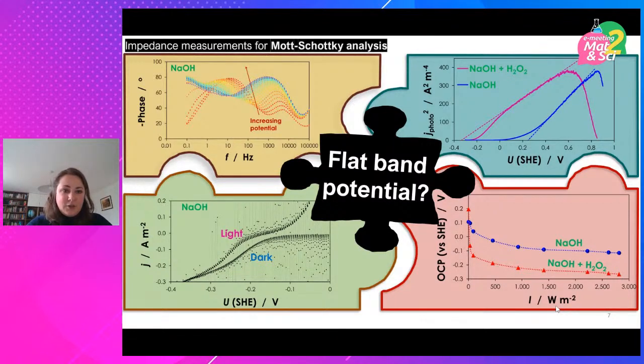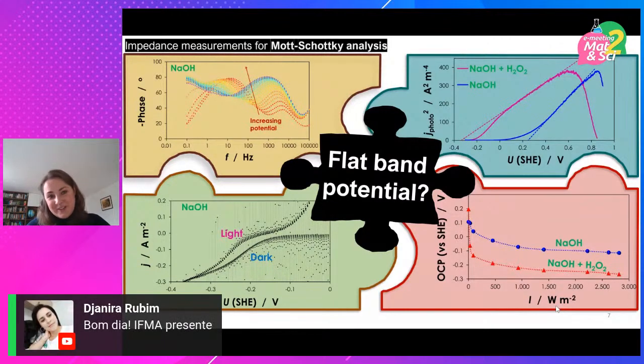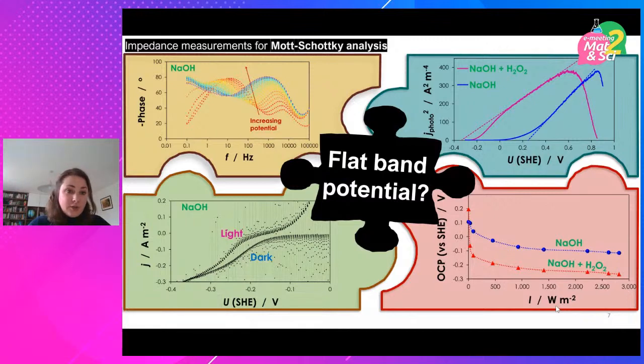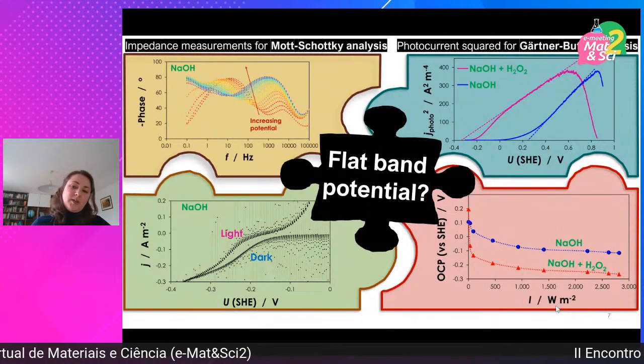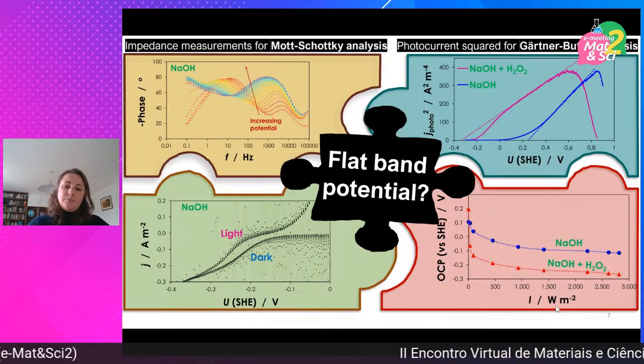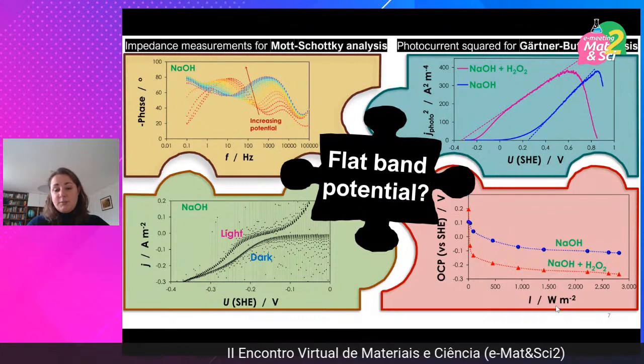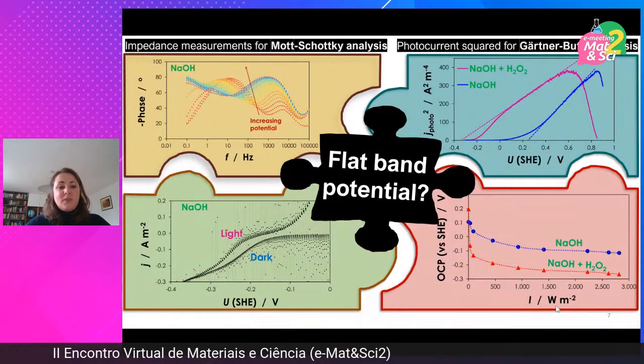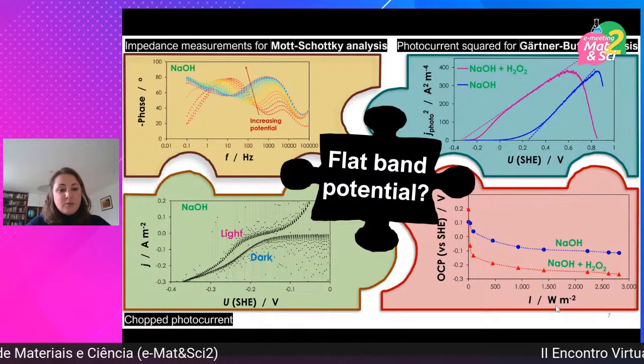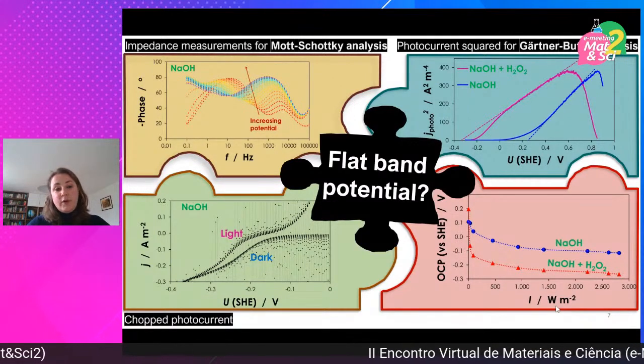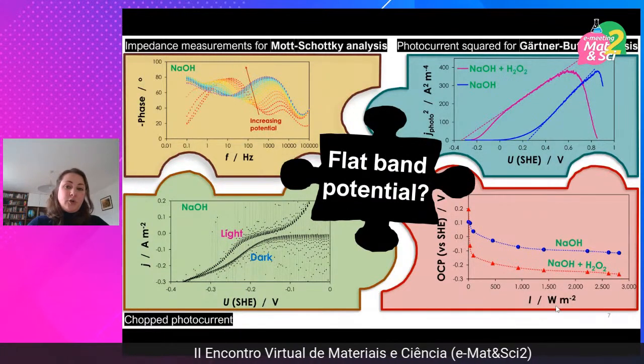So the four techniques that I used: the one that you'll probably be familiar with if you work on semiconducting photoelectrodes is impedance measurements for Mott-Schottky analysis, so capacitance as a function of applied potential. Then we have the photocurrent squared, which, according to the Gärtner-Butler equation, that idealized kinetic curve that doesn't account for any losses, if you extrapolate the linear portion of that curve to the x-axis, the x-axis intercept gives you the flat band potential in theory. Then there's the case of doing chopped photocurrent measurements, so transient measurements where a potential is modified and light is chopped on and off.